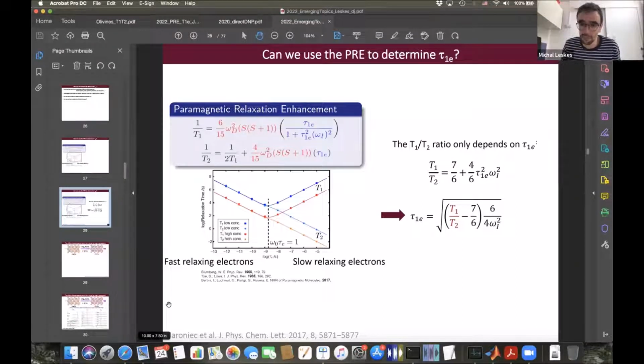And so, for lithium-6, we might be in some kind of intermediate case, because I believe that to some extent there will be some spin diffusion and direct polarization will also happen, even to far away nuclei. But for yttrium-89 and for natural abundance oxygen-17, I think it's pretty fair to estimate that there won't be any efficient spin diffusion. For example, for yttrium-89 we were looking at nearest neighbors, and the strongest possible dipole coupling is something like 5 hertz, and we are spinning at 10 kilohertz. So I think there is no contribution from spin diffusion in that case.